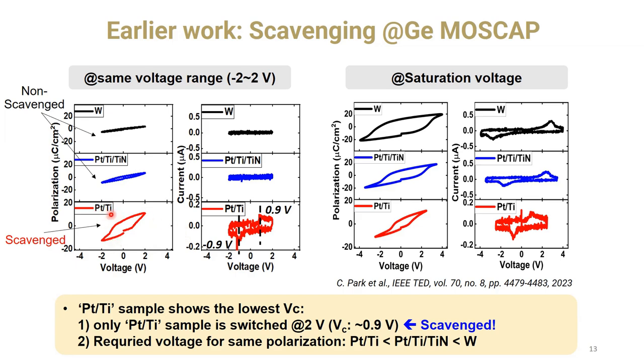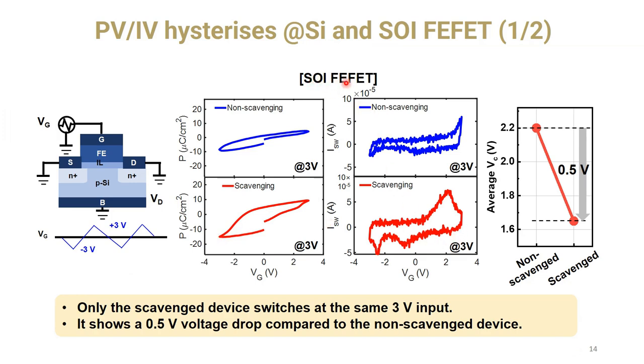The reason is that this platinum titanium metal layer is very effective at scavenging. That's why only this device shows the switching. The same methodology we applied to SOI FEFET, and we have two different devices. One is a non-scavenging device and the other one is a scavenging device. You can see here we apply the same voltage, minus 3 and 3 volt, and only the scavenging device has a nice PV and IV curve. There is a switching. In this non-scavenging device, the IL is still thick, but in the scavenging device the IL is thinner. So you can see in the average CV measurement, the voltage drop is around 0.5 volt between the non-scavenging device and the scavenging device.